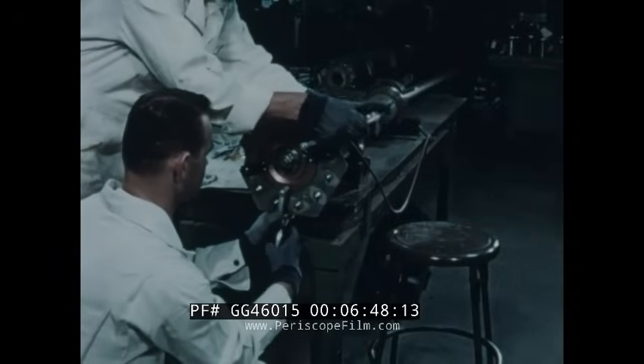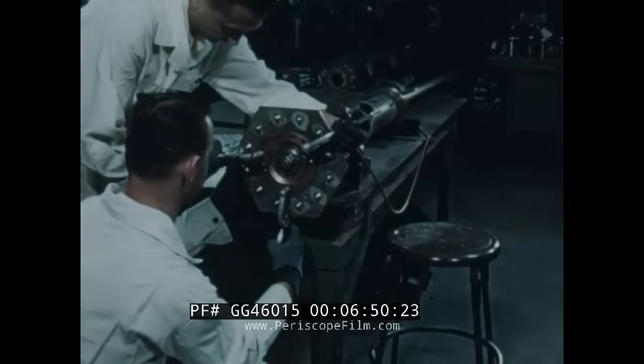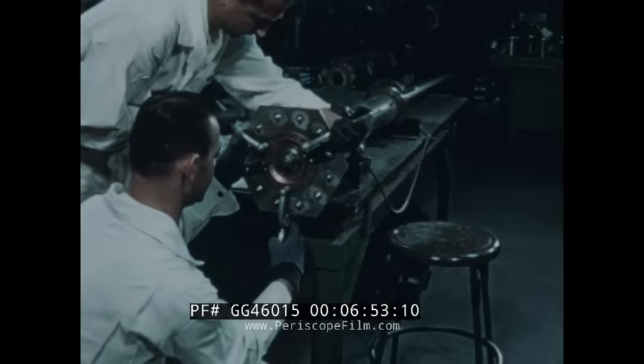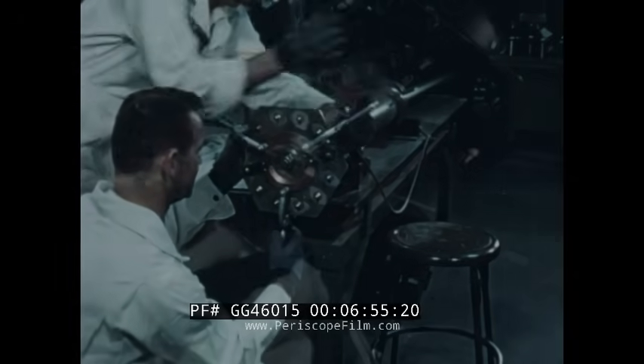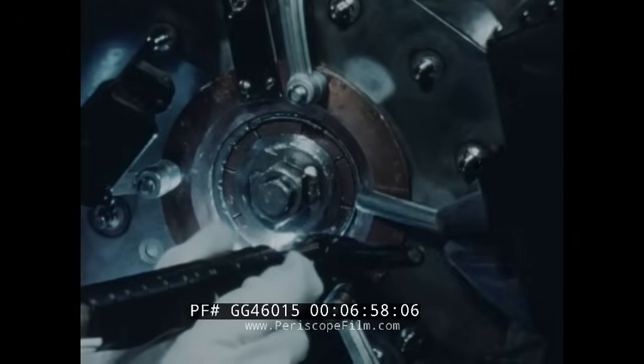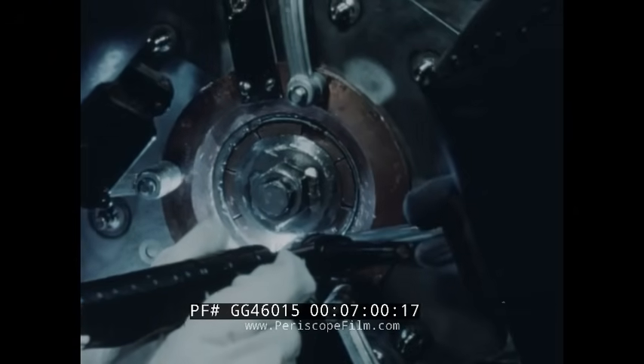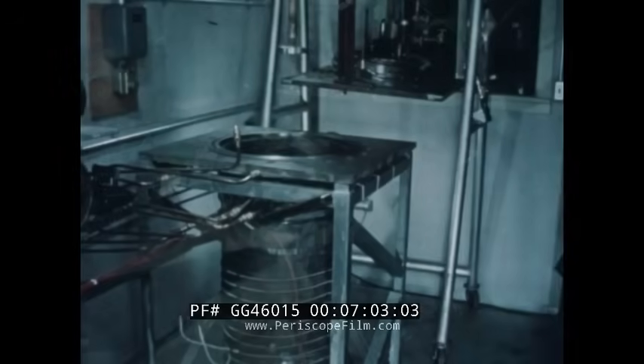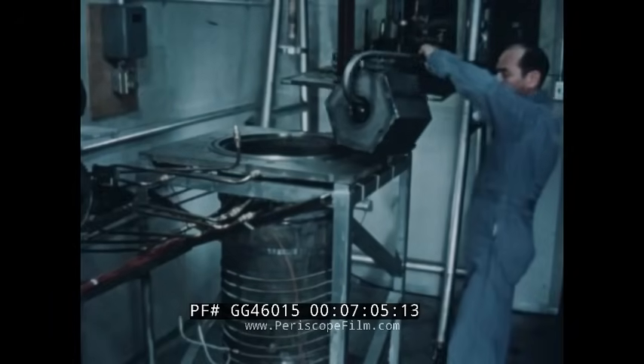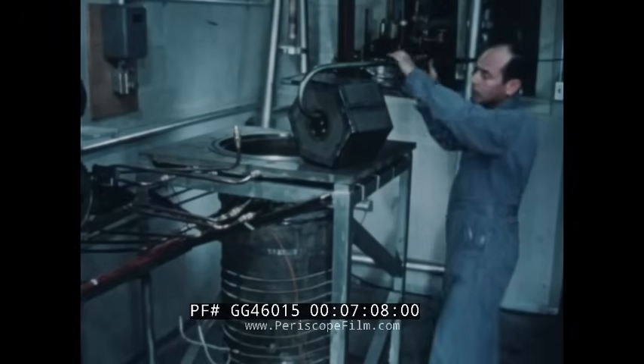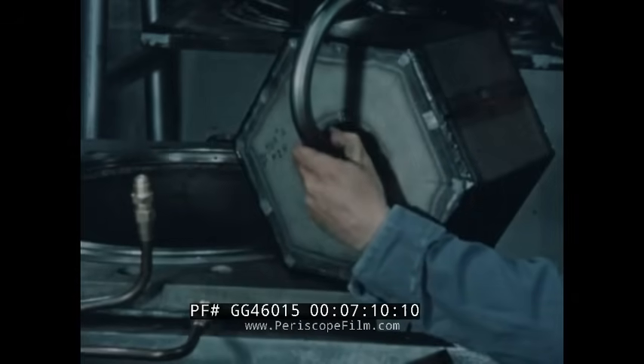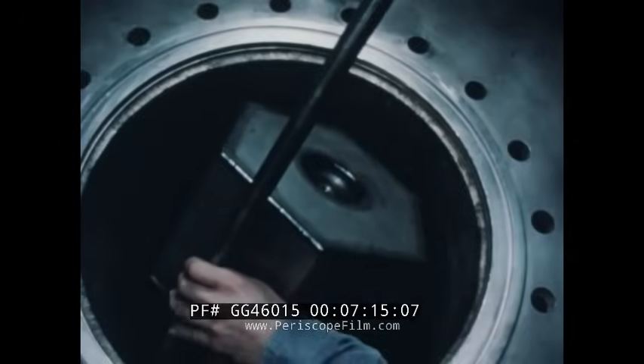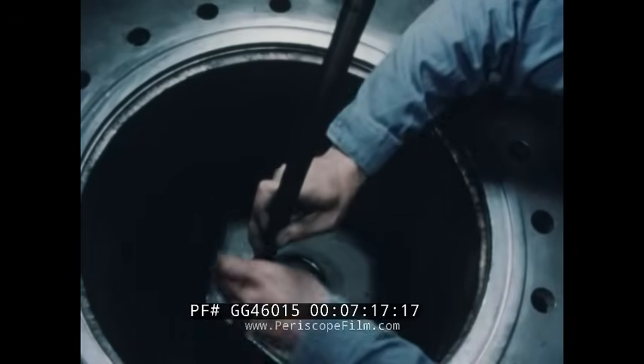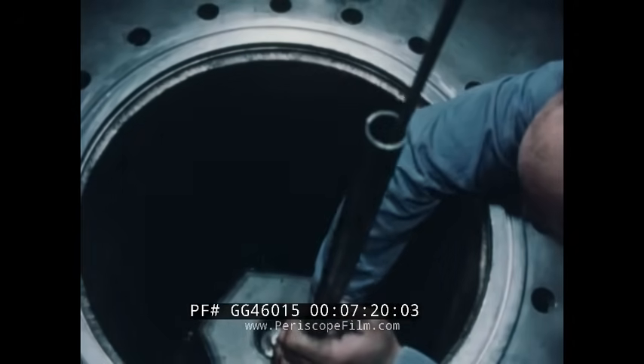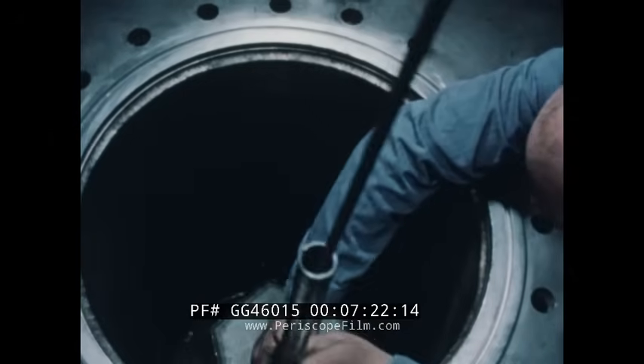The bottom end caps were heliarc welded in place. Argon under pressure within the central tube provided an inert atmosphere behind the weld. Moderator can end cap welds were investigated through mid-1955. 10-inch sections of the cans were prepared for these tests. The object was to study the possibility of buckling or cracking of the head welds due to thermal stress, which might be encountered during reactor shutdown. The thermal stress was simulated in this test by mechanical cycling.